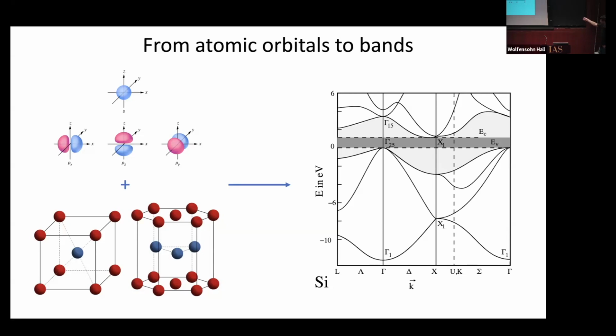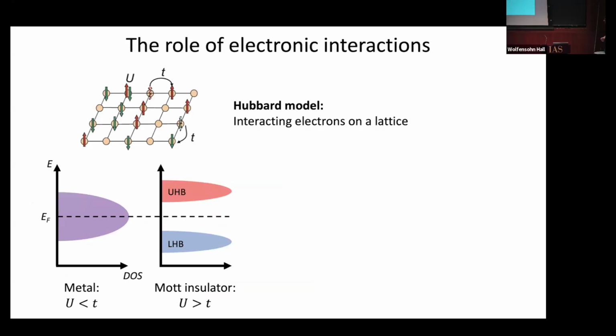That is, at a single particle level, if you just park yourself in the middle of one of these bands, you expect to have metallic behavior, and the carriers are delocalized throughout the material. On the other hand, if it just so happens that you completely fill up one of these bands, and you have no more electrons left and your Fermi level sits in the middle of a band gap, then you have an insulator or a semiconductor. This is a picture of silicon here, obviously tremendously important technologically to our society, but it's really an example of a broader phenomenon: at the single particle level, at least, we understand and can predict very well when you should get a metal and when you should get an insulator. But of course, that's only half the story.